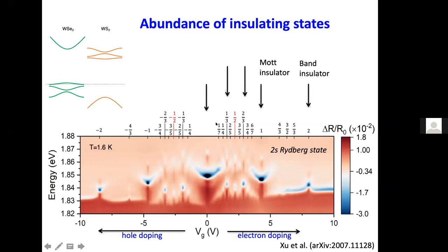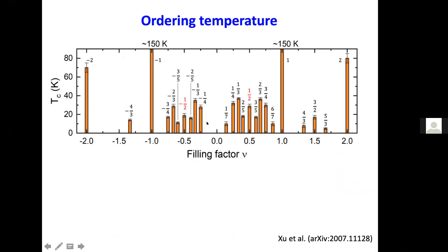The next thing to do is increase temperature and find the ordering temperature of those different states, and this is summarized in this slide. You can see insulating states on the electron side, and this is on the hole side. The electron and hole sides display almost identical correlated insulating states with similar energy scales, suggesting the same correlation effect is in play. In general, the states on the electron side seem to be stronger, which probably tells us about the U/t ratio for the two different bands.